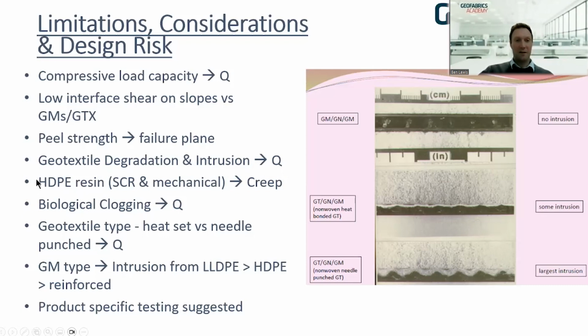The resin, I mean, not too many people think about HDPE resin performance in nets. There was a job done recently in Queensland, done by Red Earth Engineering, and they made a pretty heavy-duty HDPE net, and you rarely see that because there's not too many suppliers that have capability in doing it. But it does tend to have impact on the creep, and I suppose the creep over time of the HDPE into the flow path. Biological clogging affects flow rate. Geotextile, whether it's heat set or needle punch, affects your flow rate.